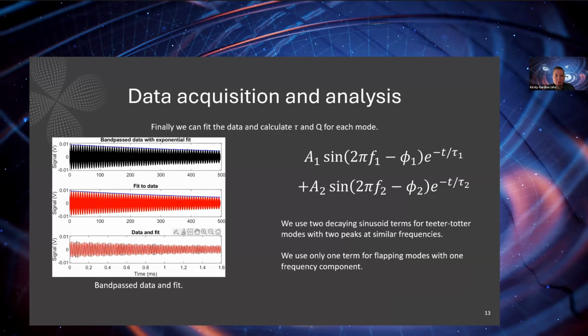So that at least helps us figure out how we fit our data. We need to use two decaying sinusoid terms, each with their own frequency, and we assume each one of them may have a different time constant and therefore a different quality factor. And so we fit our data with an equation of this form. And then typically what we do is take the average of the quality factors for those two modes to get a quality factor for the mode overall.